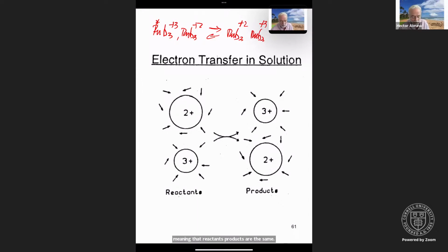However, in the transition state, a number of things have to happen. The radius of the ruthenium 3 bipyridine 3 is smaller than the ruthenium 2 because of electrostatic constriction. And so to reach the transition state, the ruthenium 3 plus has to compress a little bit. The ruthenium 2 plus has to expand a little bit. Why is that? Because again, by Franck-Condon, there can be no changes in the nuclear coordinates during the electron transfer event. And so what that means is that for outer sphere electron transfer, in this case, the structure around the reaction partners will look like a 2.5 net oxidation state. And so both have the appropriate nuclear coordinates, the electron can exchange.